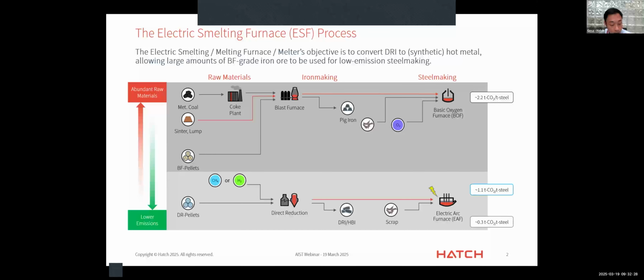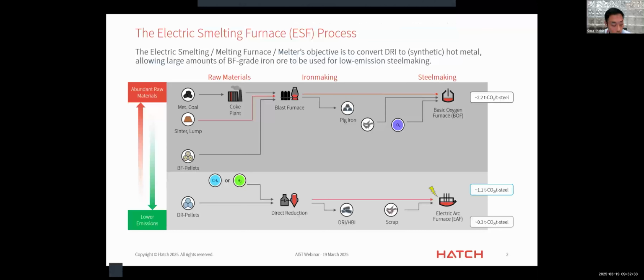On the other hand, you have the mini mill based steelmaking routes. We're using high quality raw materials such as DR grade iron ore, as well as scrap, and using lower emission reductants such as natural gas or hydrogen, making DRI, whether it's hot charged or not, turning into steel in the EAF steelmaking process. Much lower emission, but unfortunately it has some constraints, whether it's the availability of low emission reductants, but more importantly, the availability of high quality iron ore in particular, which again is quite well understood.